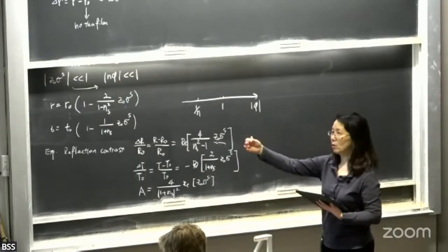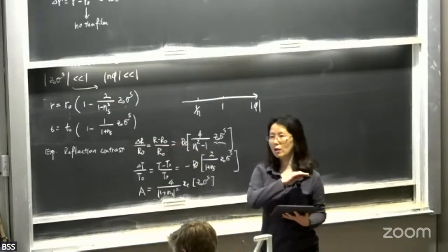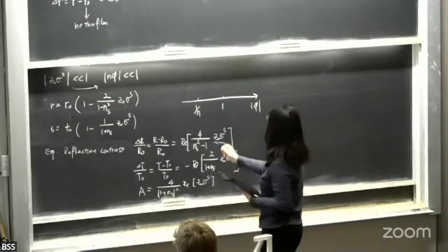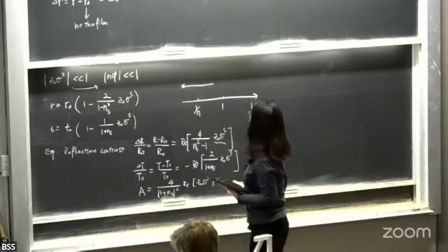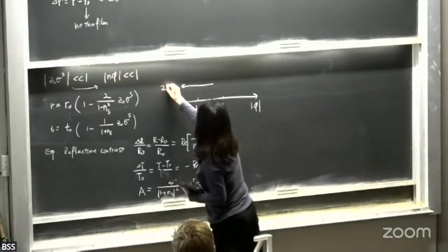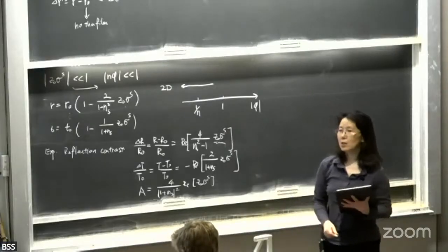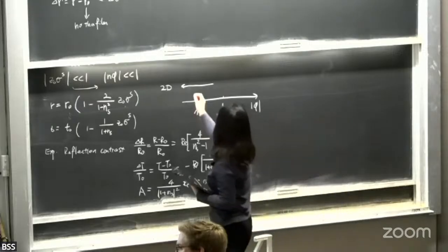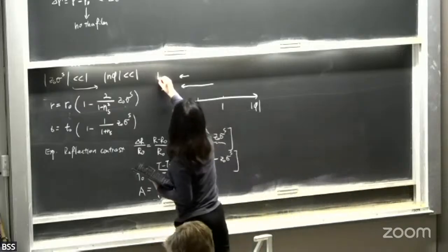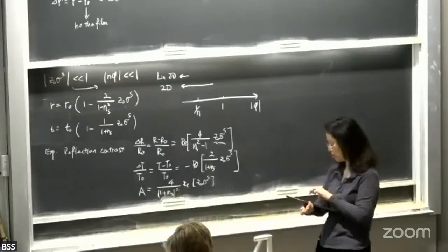For any phi, this 3D slab model is okay. It's rigorous as long as it's homogeneous, isotropic, right? But for this 2D model, we want phi to be smaller than 1, right? So this is for the 2D model, the one up there. But now if we want to use the linearized 2D model, this needs to be much smaller than 1 over n. So those are the approximations.